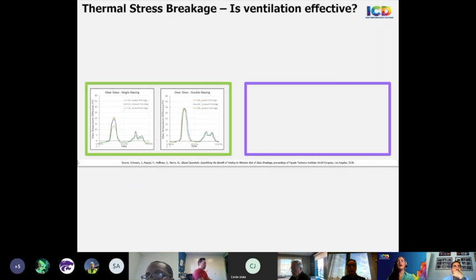So now analyzing the results of that testing, first we're looking at the graphs of the 3 conditions with clear glazing. The orange line is the sealed 4SSG, the blue line is the drained, and the green is the vented. And with monolithic glass, venting seems to have somewhat of a small beneficial effect, but all 3 are well below that danger zone of, this is in Celsius, so 35 degrees Celsius, where thermal stress breakage could happen. So spandrel ventilation does not make a difference. And with insulated units, there's not much of a difference between the three options, and we're just starting to reach the level of danger of thermal stress breakage.